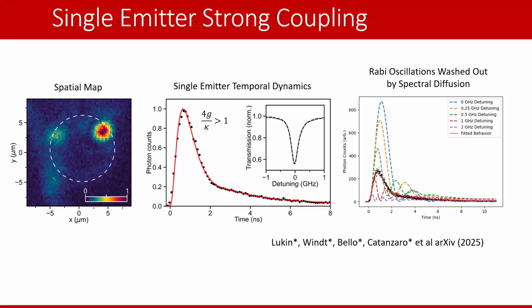And we are within the regime where we'd expect this, but because the defect moves in time, every time we sample photons that come out of the system, we're actually averaging over many spectral detunings. And this gives rise to this sad little knee instead of the Rabi oscillations that you would expect from a strongly coupled system.